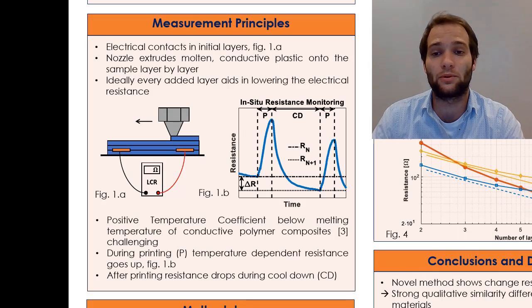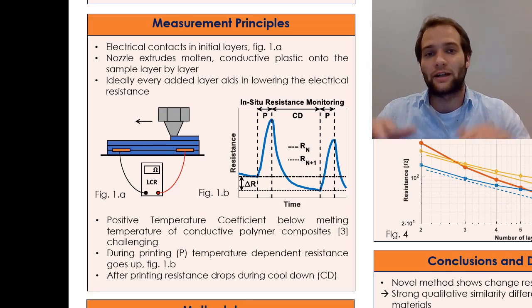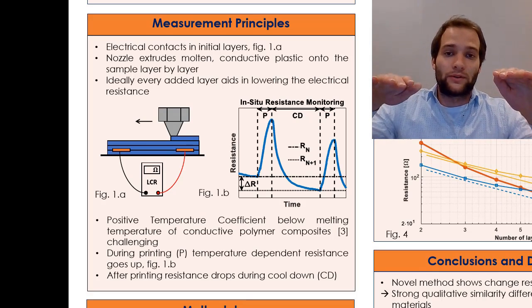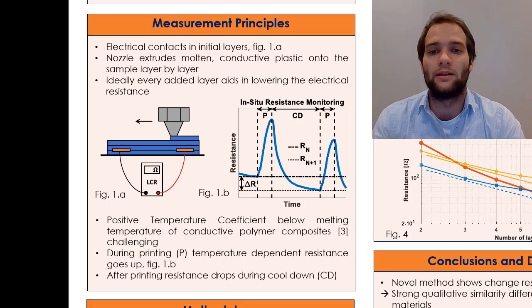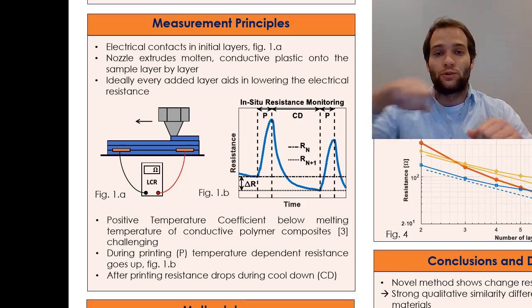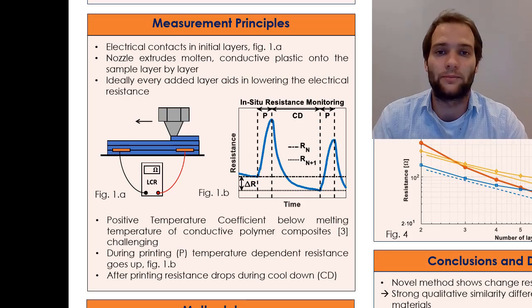The measurement principle is based on standard electrical resistance measurements where electrical contacts are either placed on the printing bed or in one of the first layers of the sample. And when the nozzle extrudes molten conductive polymer, the change in resistance can be measured. And ideally, every layer added to the sample aids in lowering the total resistance.